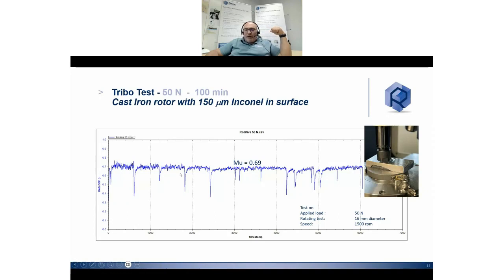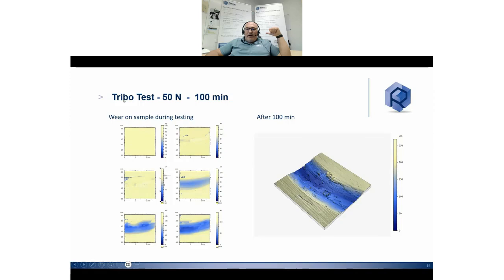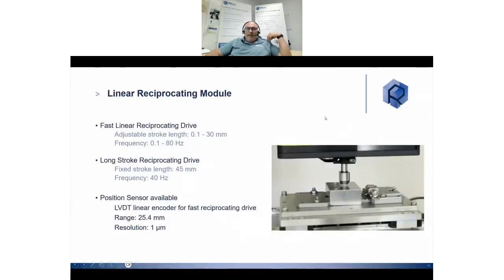We have a friction coefficient at 0.69. We apply 50 Newton with a 16 millimeter diameter. It's really ball on disc on this type of rotor with a speed of 1,500 RPM. And here you see clearly the increase of wear during the test and the final wear at the end of the test. And this one helps you to understand clearly what happened in rotary.